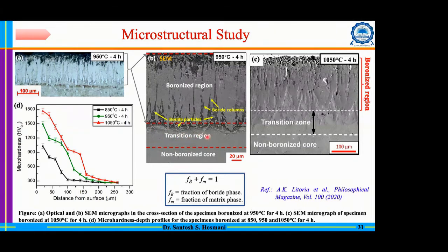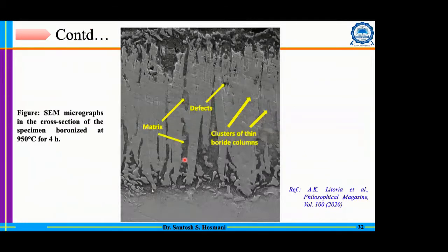In principle, to understand the mechanism of the process, we have to read this diagram in the opposite sequence, that means core to surface. Why is that so? Because initially we have a non-boronized material. As you go further, there is a formation of tiny borides, most likely at the grain boundaries, and then they grow in a particular direction and form the columns. So this figure itself is telling us the mechanism, how the situation could have occurred. Just imagine the process from the core to surface. In the next slide also, I will imagine this in the opposite sequence, whenever I show the chemistry of this region.